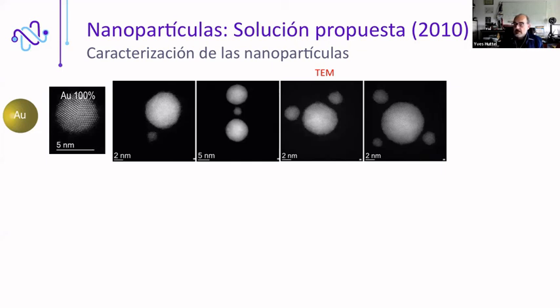It is not clear what is the best geometry, but it has something to do with the thermodynamics of the fluids, for sure. And unfortunately, we don't have the tools to make all these studies. But in that case, for the TEM images, what we do is to place a TEM grid in front of the beam, which is much easier than to deposit on a substrate and then try to transfer on the TEM grid.